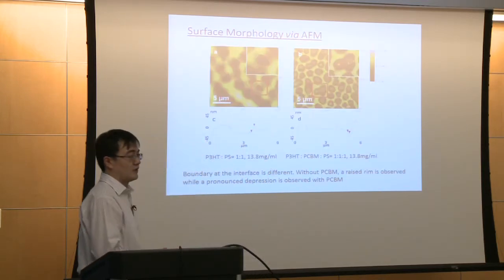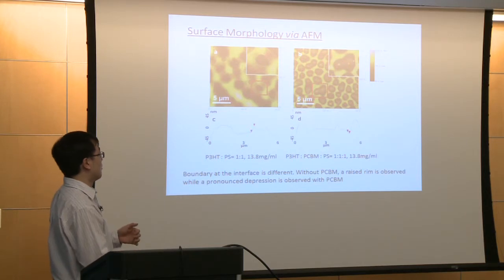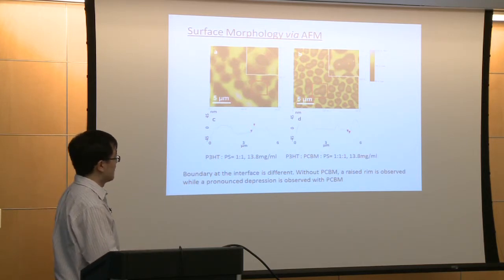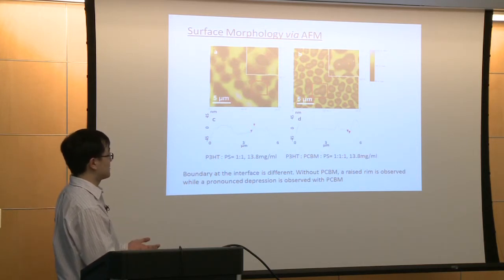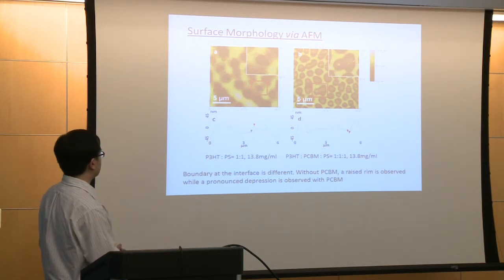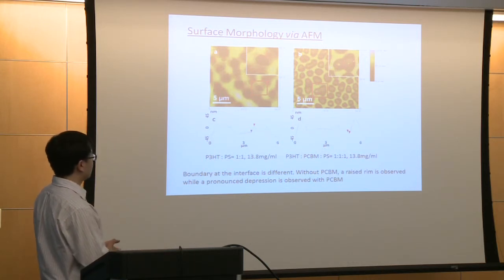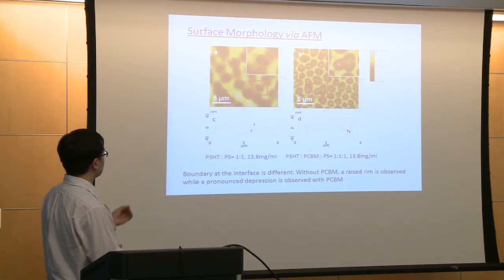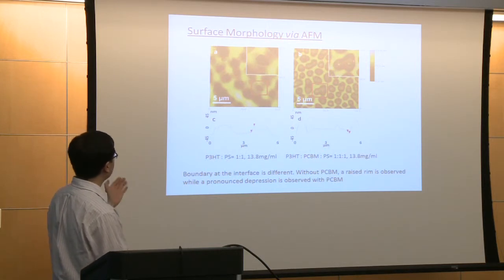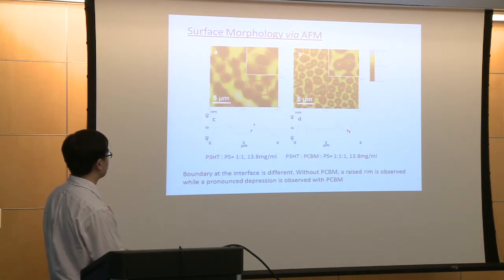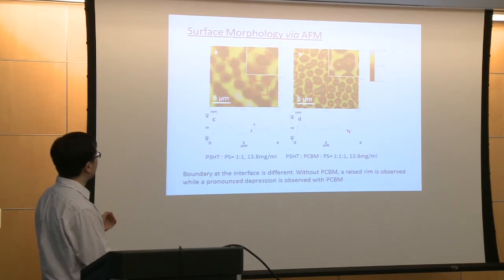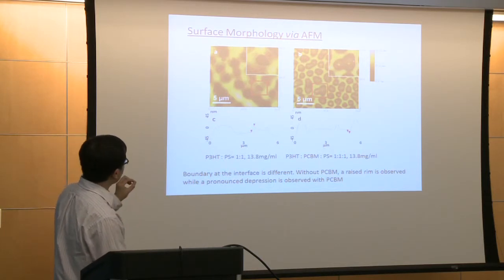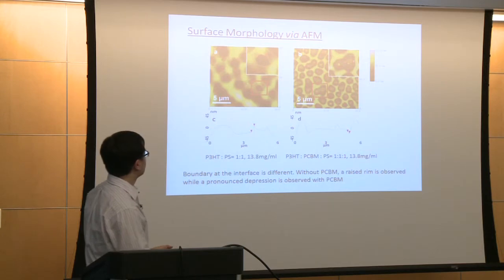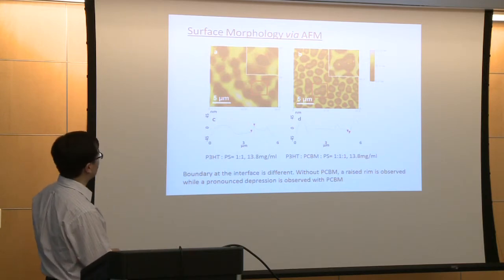And we are also very interested in what the difference is in the surface morphology with or without the PCBM. So we did that, and we indeed find some difference. Figure A is the surface morphology of the sample without PCBM. Maybe you cannot see clearly, but you can see the enlarged picture on the right corner.